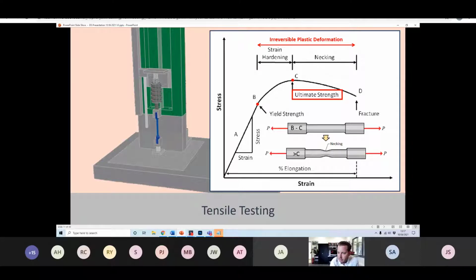Once we reach the UTS though, or the ultimate tensile strength, things begin to change and the test specimen actually starts to neck. And you can see an example in the inserted image where at this point the stresses and strains within the specimen actually no longer remain uniform or uniaxial, as is the case during the uniform straining portion of that test. They become far more complex than this, and at that point interpretation of these curves becomes much more difficult as the material is now heading very fast towards its final failure stage.